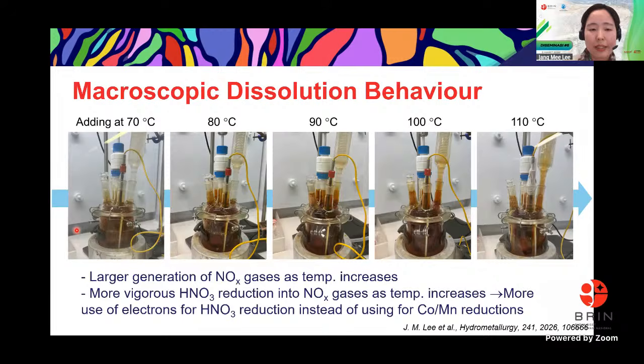As you can see here, these are photos right after adding the reductant at different temperatures. You can see this reddish brown color, which is the nitrogen dioxide gas, and it may also include nitrogen oxide gas. This is the result of the reduction of the nitric acid solution. As the temperature increases, the reddish brown gas evolved more. So it may indicate that at higher temperature, after adding the reductant, the nitric acid was reduced more, and less of the reductant reduced the manganese and cobalt from the laterite ore. So we would say this is because of the competing reaction.